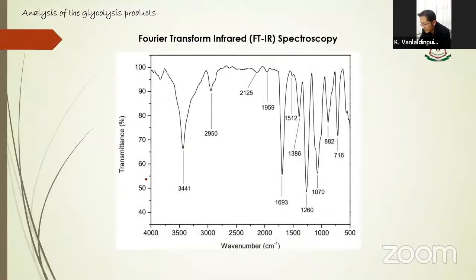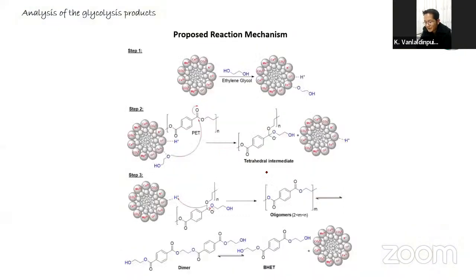Then this is the IR spectrum of the recrystallized PET. This is due to OH. This is due to the presence of the methylene group, CH2. And this is the carbonyl. We used this technique to detect the functional groups present in the compound. And we have proposed this reaction mechanism for the PET depolymerization.